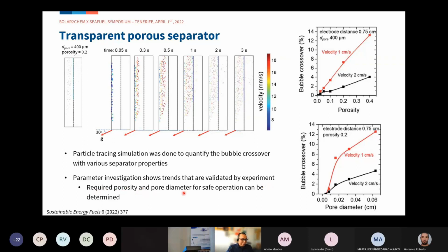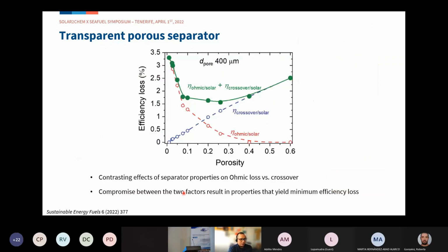To summarize the impact on ohmic loss and crossover, we have this plot over here where we see the efficiency loss as a function of porosity. With increasing porosity, ohmic losses shown in red decrease, so we have lower and lower ohmic loss with more porosity, but at the same time we have a competing effect of crossover. This competing effect needs to be counterbalanced and compromised in order to arrive at the minimum efficiency loss. For this particular case of pore diameter of 400 microns, we see that 25% porosity, for example, results in minimum efficiency loss.